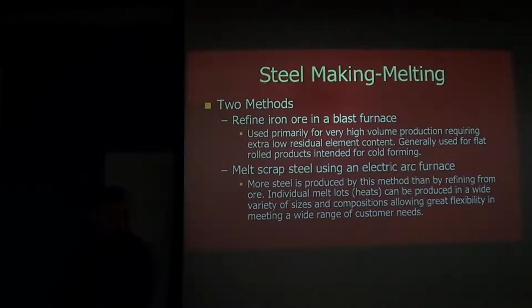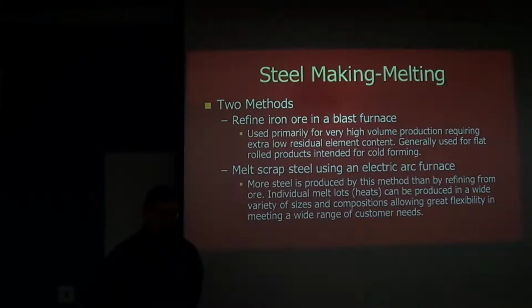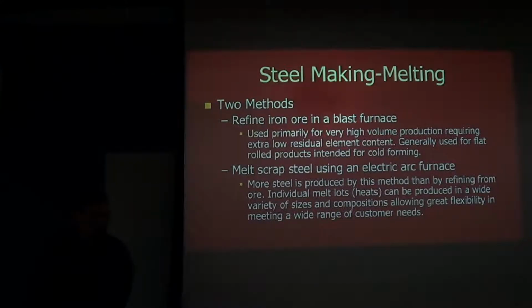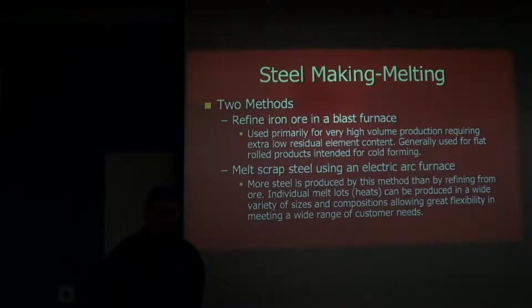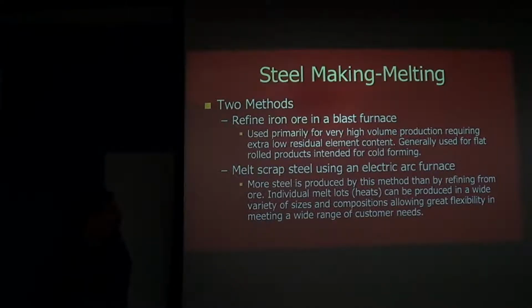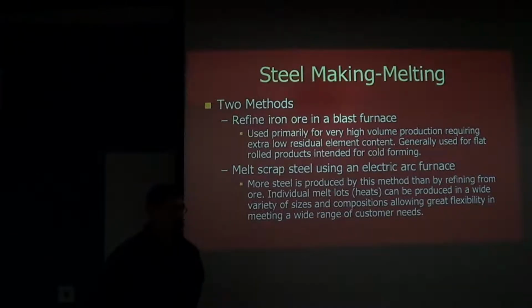To refine iron from iron ore, the method used is a blast furnace. You take iron ore and put it into a hollow tower that's multiple stories tall, probably between 3 and 5 stories. You pour iron ore into it, then some limestone, and then some coke, and you alternate those materials going up the stack. At the bottom of the stack you would have huge, enormous blowers. Sometimes you might even have additional burners down there.